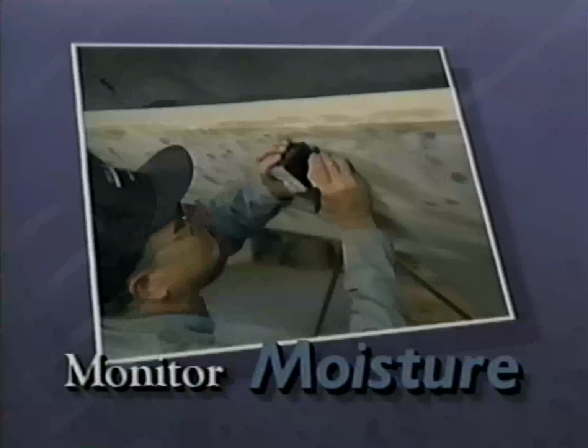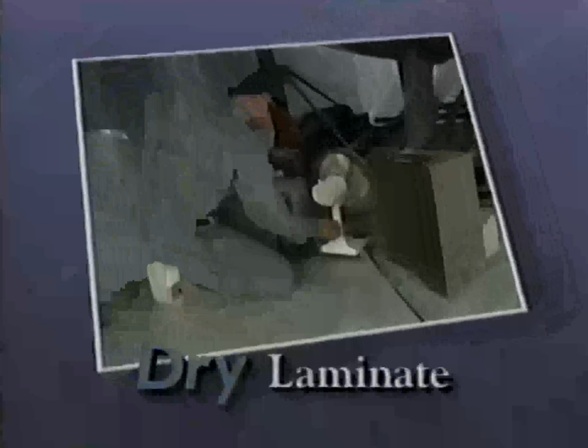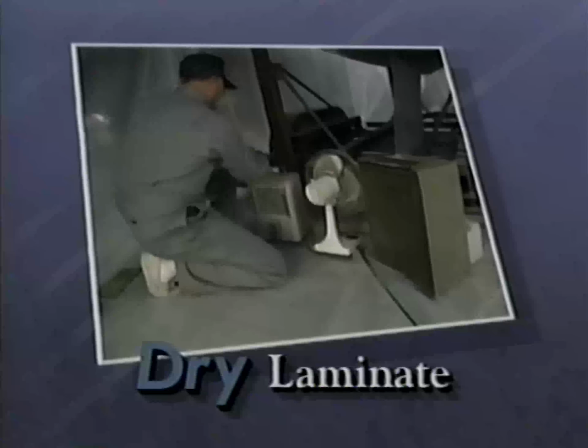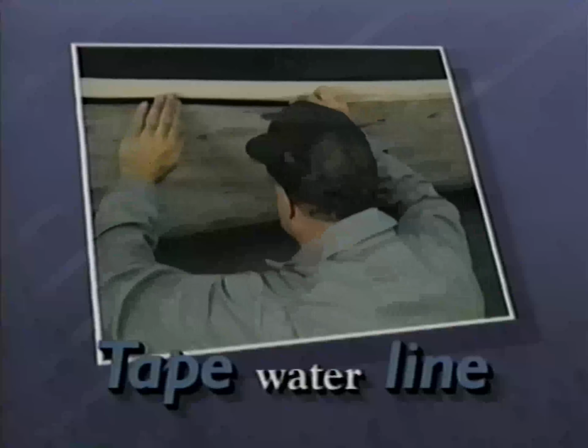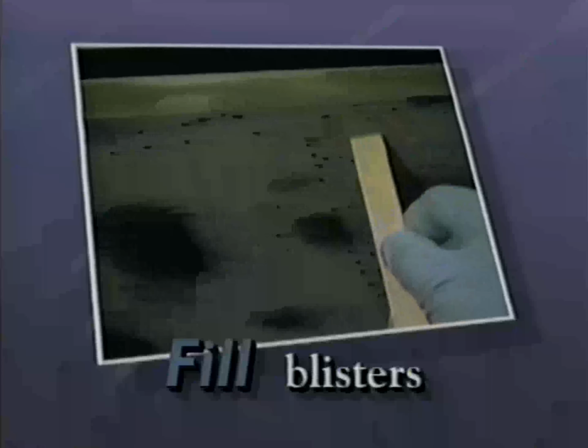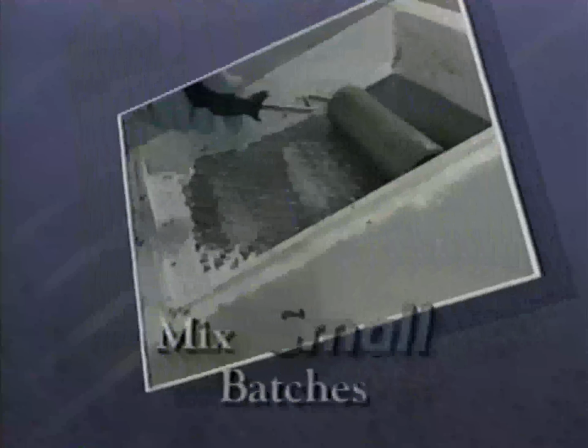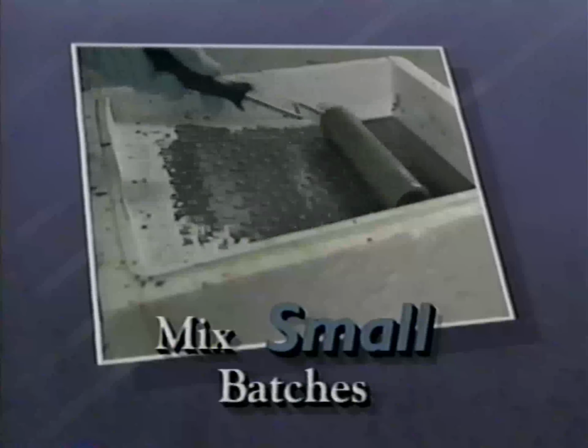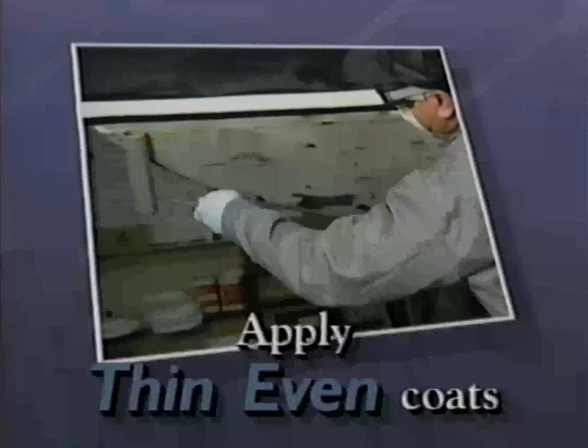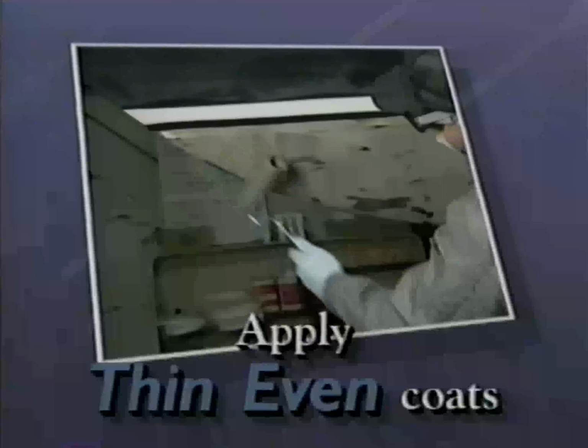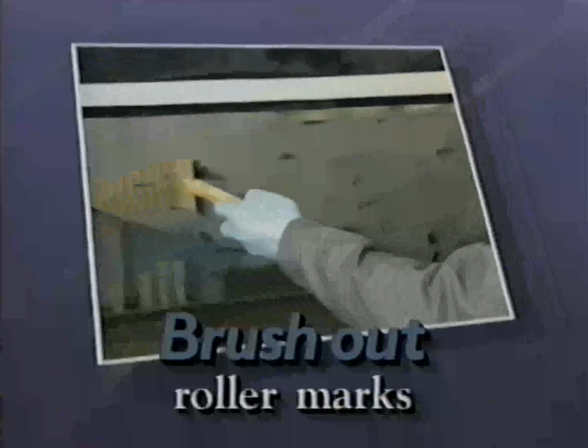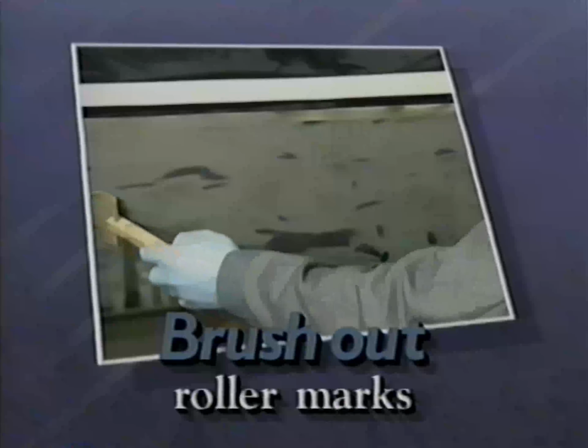Monitor moisture content. Dry laminate. Tape waterline with vinyl tape. Fill blister cavities with low-density filler. Mix small batches of epoxy. Apply thin, even coats with an 800 foam roller. Brush out roller marks by alternating brush strokes for each layer.